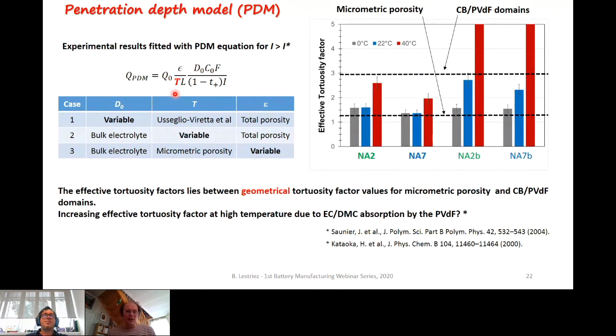And then we considered as the variable parameter the tortuosity factor. We considered the total porosity and the bulk electrolyte diffusivity. The results are here plotted for the 4 electrodes for the different temperatures, and they are compared with the geometrical tortuosity factor values for the micrometric porosity and for the CB-PVDF domains. So for most of the electrodes, and considering the various temperatures, you can see that the effective tortuosity factors are in between that for the micrometric porosity and that for the CB-PVDF domains, which is an interesting result, because we could have expected that the effective tortuosity factor would be a mean value representing the whole of the architecture.